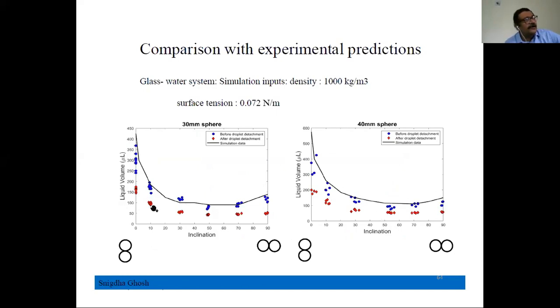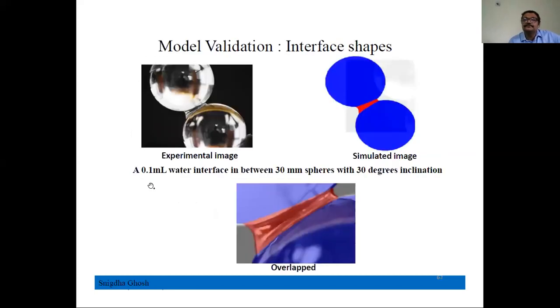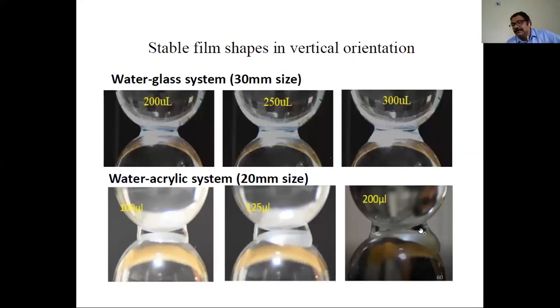Of course, there are more complex issues. The actual hold up in the packed bed will be less, because this can be extended to a packed bed, since a packed bed can be thought of as a distribution of these different orientations. So we can extend it to the packed bed and find out the hold up. But there is a problem here. In an actual packed bed, once the liquid forms, it will drip out. When it drips out, some part will pull back and some part will fall down. So the actual hold up will not be the maximum. It will be somewhere in between the maximum and what was pulled back and remained.